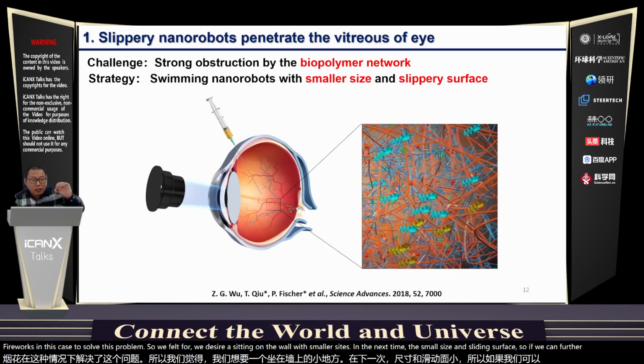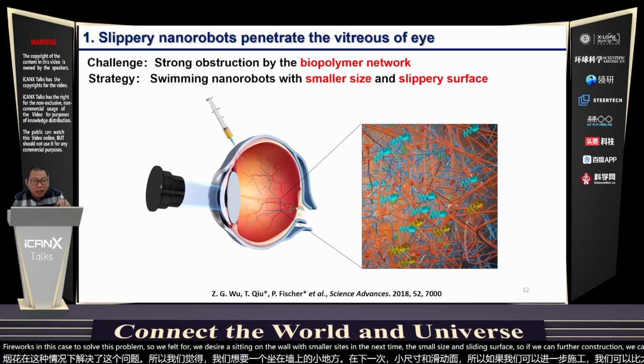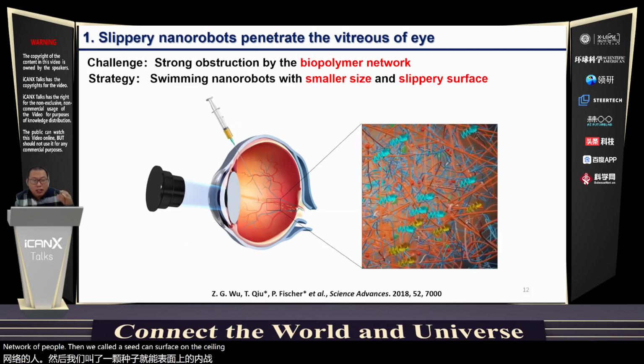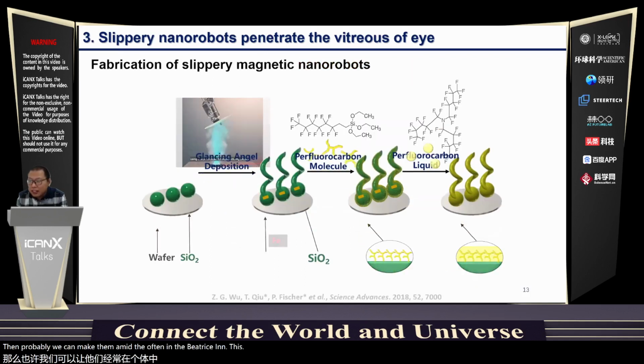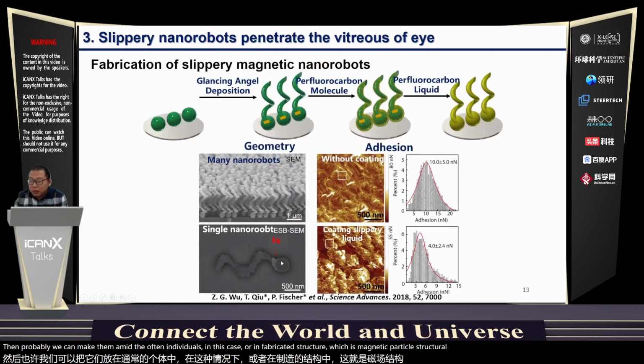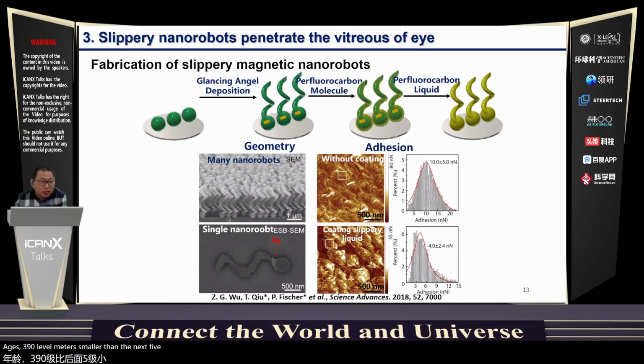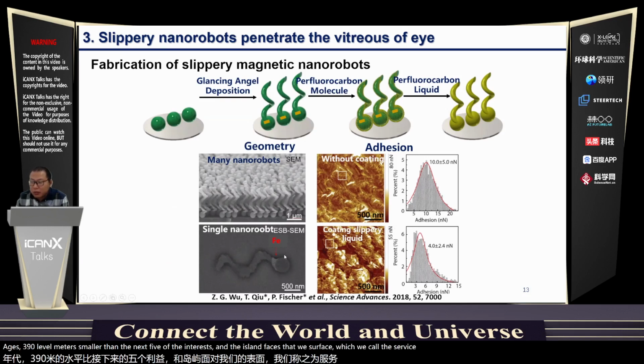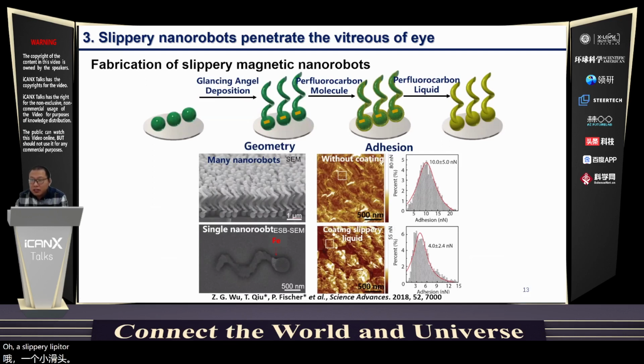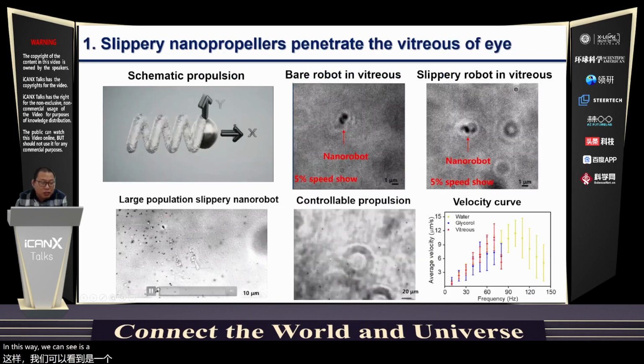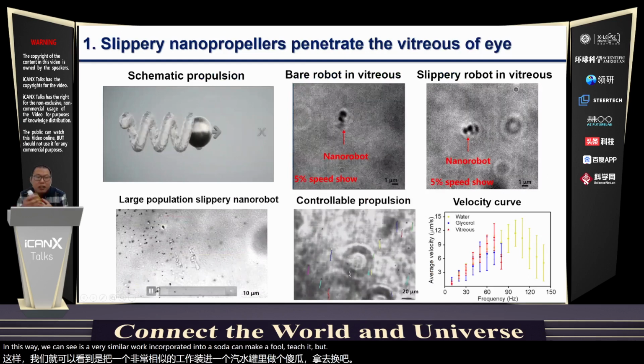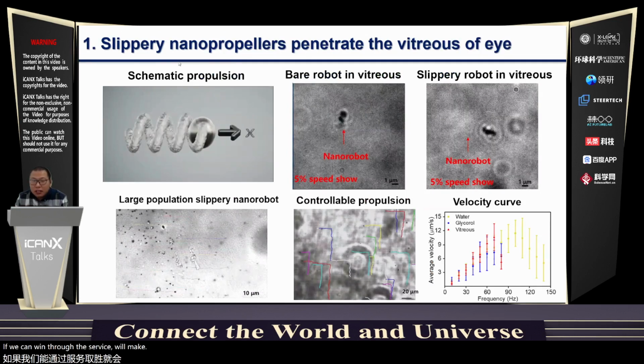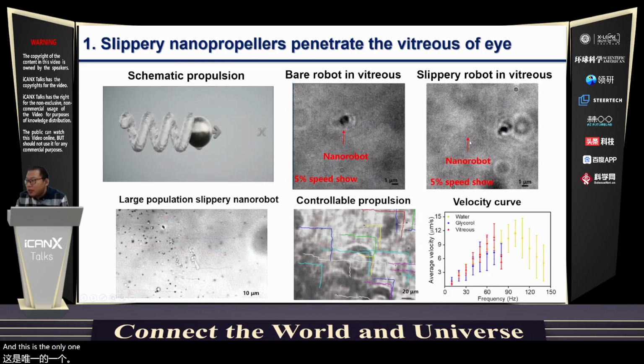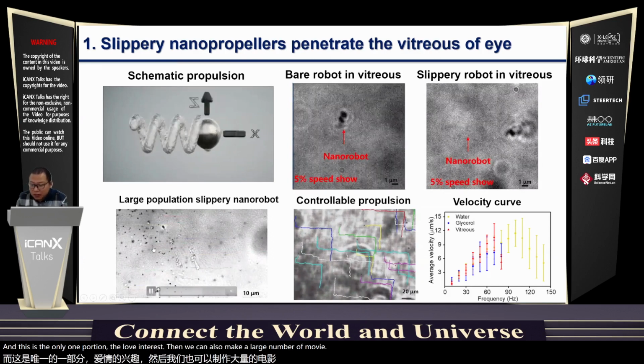If we can fabricate a structure which is smaller than the mesh size of the network of the vitreous, and then coat a slippery surface on the swimming robot, then probably we can achieve propulsion in the vitreous. So we fabricate a magnetic helical structure with a height of 380 to 390 nanometers, smaller than the mesh size of the vitreous. And we coat the surface with a slippery lipid layer. In this case, the adhesion of the surface is dramatically decreased. You can see a bare swimming helical robot in the vitreous cannot make a full rotation, but if we coat it with a slippery surface, it can propel in our vitreous. And this is only one robot propelling in the vitreous. We can also make a large number of slippery robots move through the vitreous of the eye.